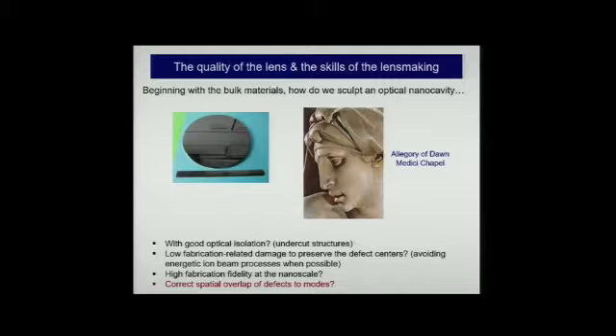These are single vacancies. So think how fragile that material is. Anytime we hit it with electron beams, anytime we hit it with an ion beam, aren't we likely to rattle the crystal structure and remove atoms? So in particular, in fabricating these structures, we have to be very respectful of the material and utilize processes that are least likely to introduce additional, unwanted defects to the material.